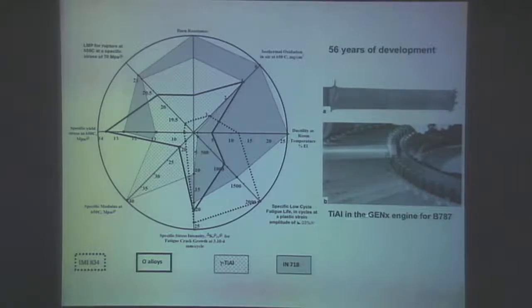Well, here's an example of a new titanium alloy used in today's engine, which powers the Boeing 787. This is an intermetallic, okay? And I won't go through this in detail, but all I want to tell you is that this intermetallic, TiAl, provides a transition between conventional titanium alloys, which have temperature limits at 500, and nickel-based alloys, so that you can start using these at about 600 to 700 degrees centigrade, not in replacement of the highest temperature nickel-based superalloys. But I also want to point out to you that the development of this intermetallic took 56 years, okay, since the start of work on this material to its final use in the aero engine.